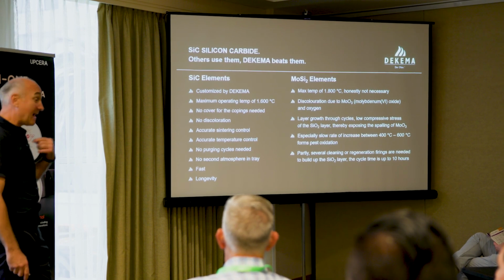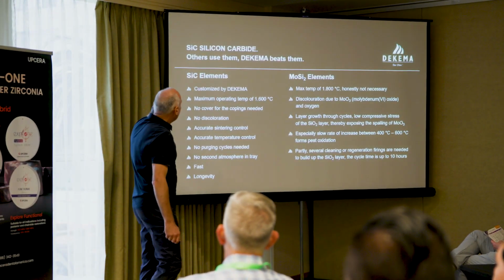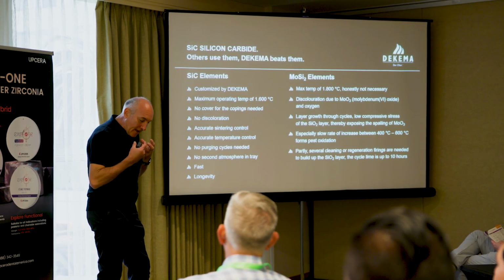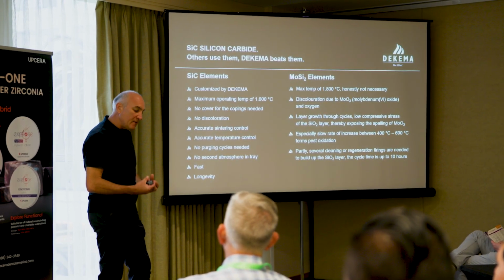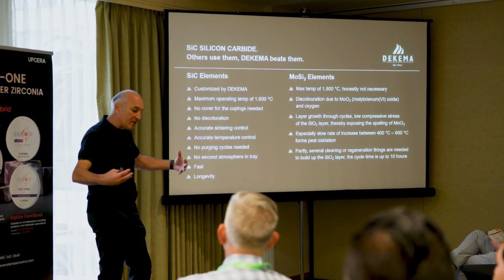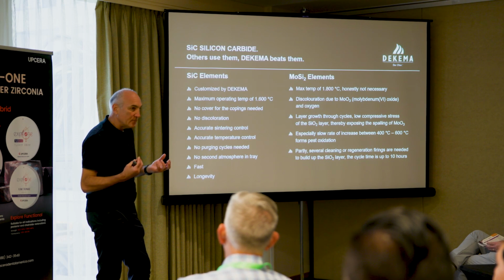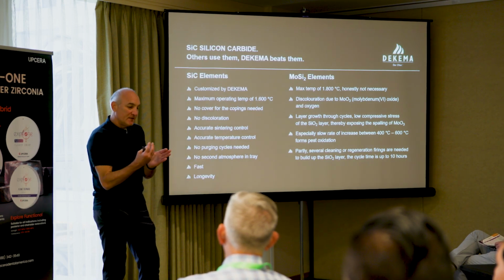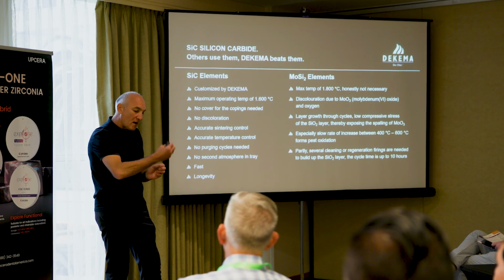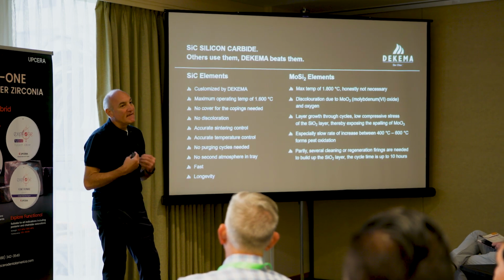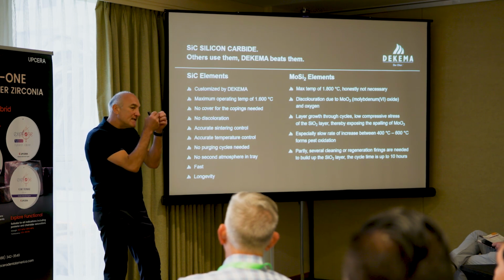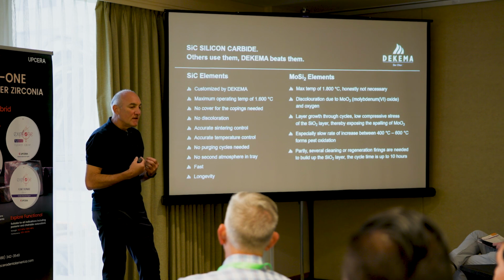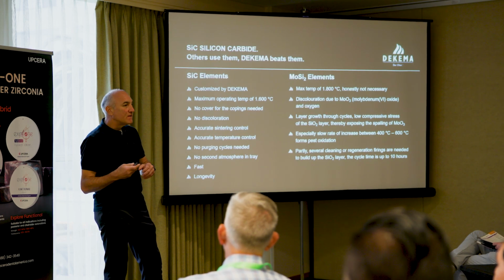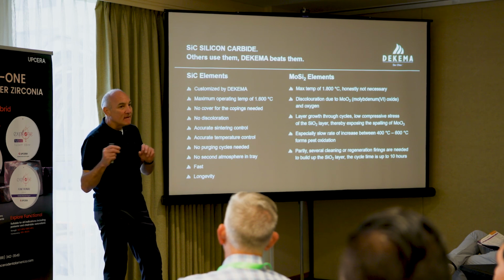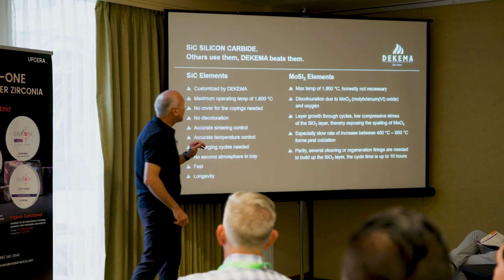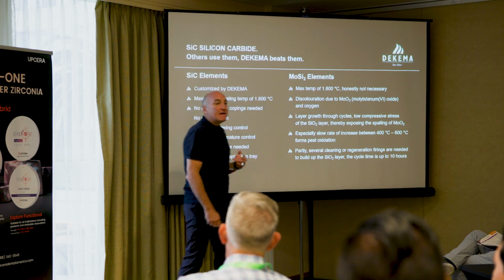MoSi2 pest, in my words. Why? Again, SiC elements have an inert cleanness. And if you heat with SiC, the SiC element cannot accumulate pollution. MoSi is exactly the difference. With a MoSi element, you always have a glass layer around which saves you from pollution. Because inside this MoSi element, you always have inert accumulation of different rare earths, of different polluting, greening, discoloring materials. And these glass layers reduce.